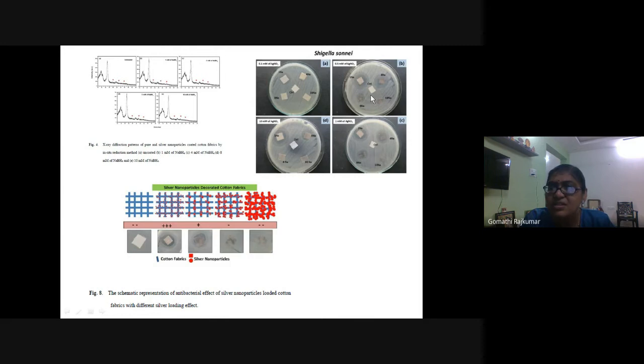So the cotton fabric showed a very good zone of inhibition, which showed us that when we supplement this to cotton fabric in the future, I think so far people are just using silver meshes, but not silver oxide nanoparticle substituted cotton fabrics. These nanofabrics are not in usage. So when these nanoparticles are coated onto the fabric, this could make surgery easier. In case of all internal and external sutures, if these cotton materials are coated with silver oxide nanoparticles that have been reduced, I think this could pave the way for very good surgical equipment.